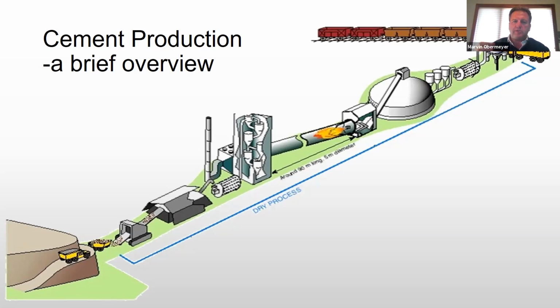The preheater towers basically are preheating and drying the material, okay? The material goes through these preheater towers, through these little cyclones. It utilizes all of the heat, the passive heat, if you will, from the kiln over here and from the clinker cooler, which is here. We're going to get to that in a second. Once that material is brought down here to the final stage, it's already pre-calcined and it's already at about 1,000 degrees before it even goes into the kiln.